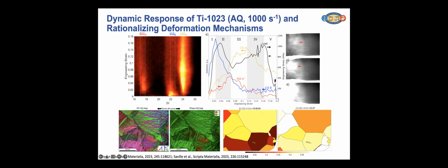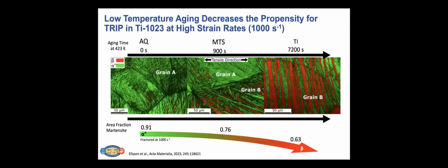Shown here in black is our stress-strain response, and it has a funny shape just because of the ringing that's experienced during the test. We see in blue the matrix phase decreasing, commensurate with the increase in the formation of martensite, so evidence for TRIP in the microstructure. From the imaging, we can get information about the extent of necking and the elongation. And then we can do postmortem analysis, and clearly with crystallographic mapping, we're seeing the formation of martensite. And then work we're doing more recently is rationalizing the different mechanisms that we see that are present, and whether we have the potential for TRIP, for example, in a hard or a soft grain orientation. Aging these microstructures impacts the propensity to undergo transformation-induced plasticity. So that's something to consider as well.